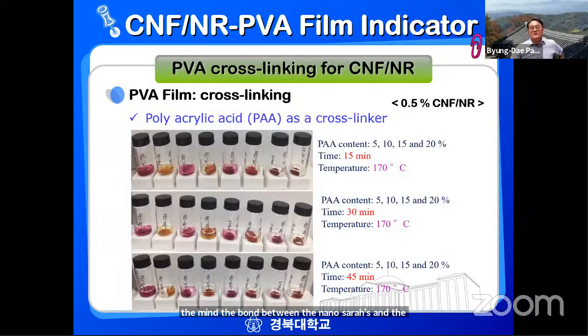And then this time we used PVA, polyvinyl alcohol. As you know, PVA is a water soluble polymer. When you use it, it's soluble in water, so we don't want this kind of problem. So we use polyacrylic acid as a cross-linker to cross-link the PVA polymers. So we have different PAA concentrations from 5%, 20%, and different heating times for the cross-linking process, 15 minutes, 30 minutes, 45 minutes, and the temperature is fixed at 170 degrees Celsius.